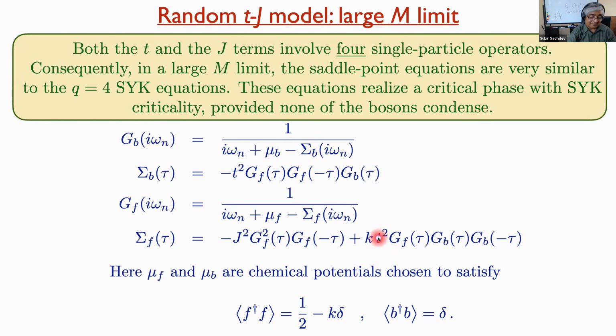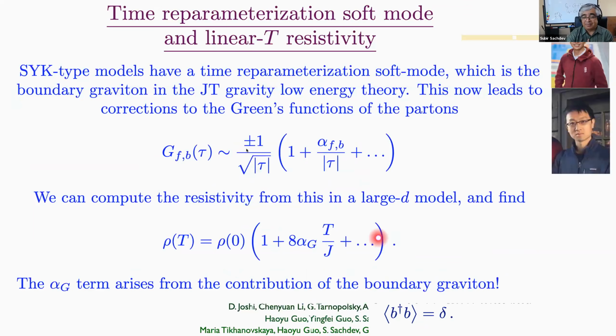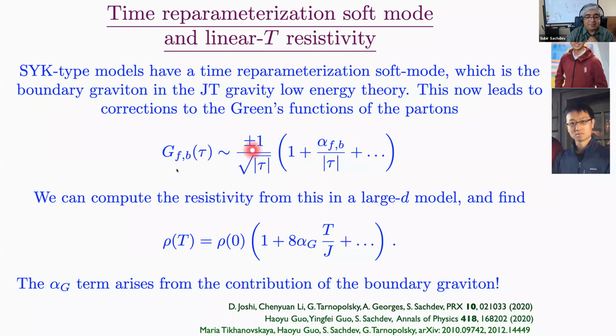But as you know, the solution of these equations is incredibly rich. The leading behavior is 1 over square root of tau. This is just like in the Majorana SYK. Both the fermions and the bosons have the same 1 over square root of tau. And also, like in the Majorana SYK, the first correction is 1 over tau with a coefficient, which is called alpha G by Maldacena and Stanford. So we just call it alpha F and alpha B because those are two different numbers that we can, in fact, compute from the coefficient of the Schwarzian, the value of the boundary graviton. So it's only one parameter, the coefficient of the Schwarzian, from which you can get alpha F, alpha B, and also this coefficient of linear resistivity. They're all related to the same unknown UV sensitive quantity.